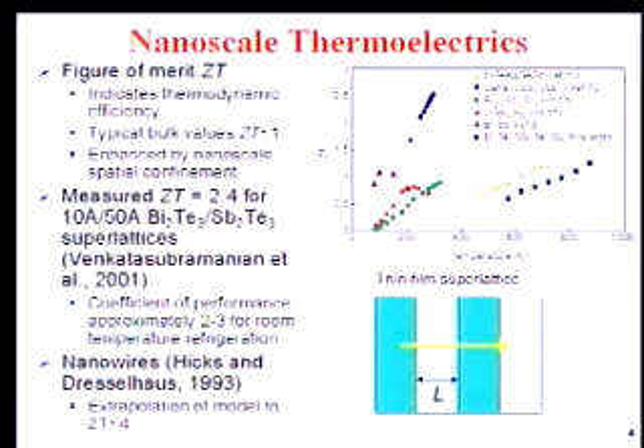So the point here is that certainly there could be significant materials developments and using different materials, but essentially this material operates on the principle of allowing significant electron transport while interfering with phonon transport. At least that's what people think. And so making things smaller may not help. In fact, when they went to the 50 angstrom layer, made that smaller, it didn't always make anything better. So making it smaller is not always better.